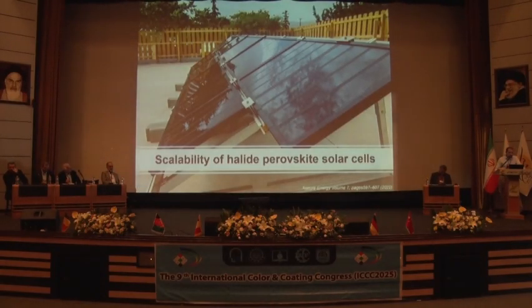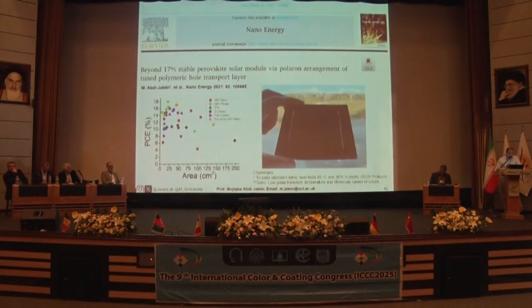Now let's talk about the scalability of this technology. One of the challenges, if we want to go from lab scale to larger scale, is in terms of their lifetime in operation. Basically, one of the challenges is high temperature. You can imagine real solar photovoltaics normally go to high temperatures like 50, and even in some places like here, it can go up to 80 degrees, the temperature of the PV module. So that means the material or the device we develop needs to be stable at that high temperature.